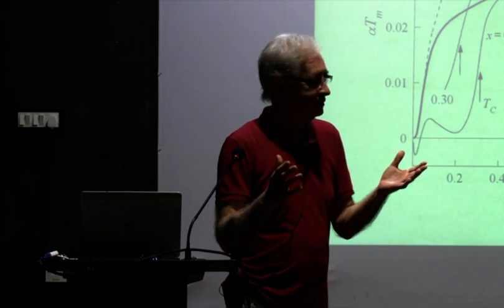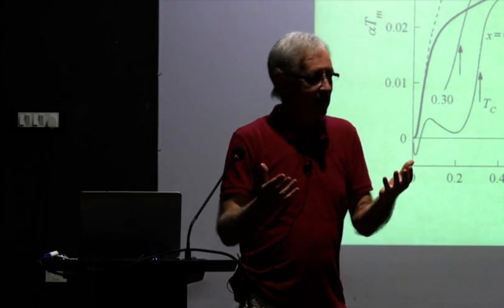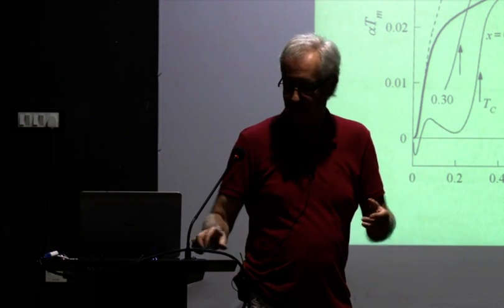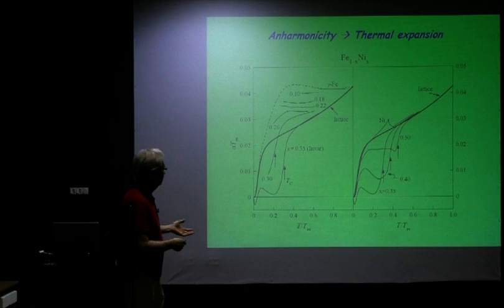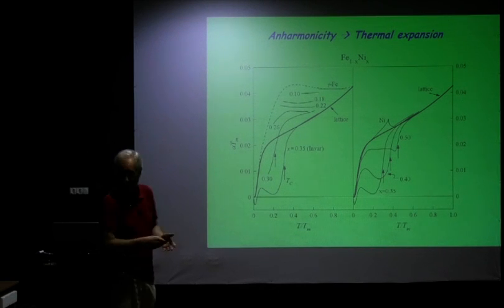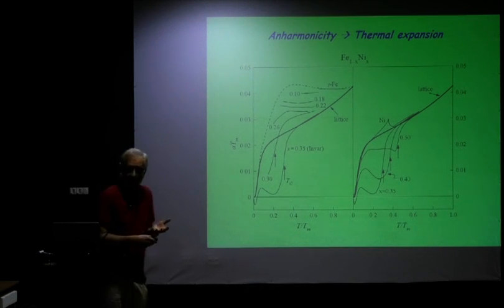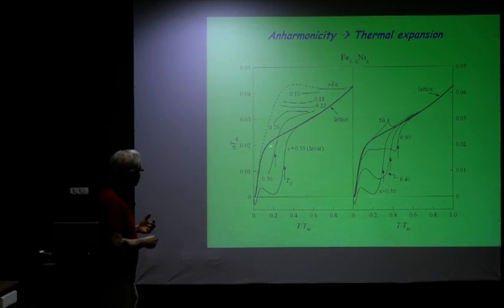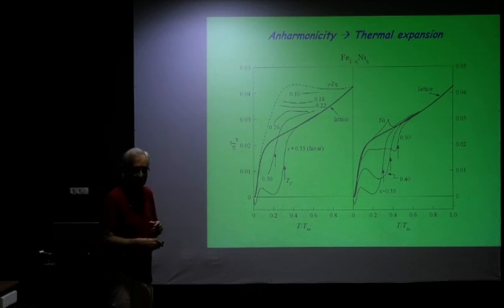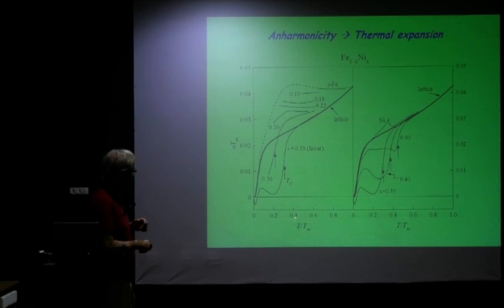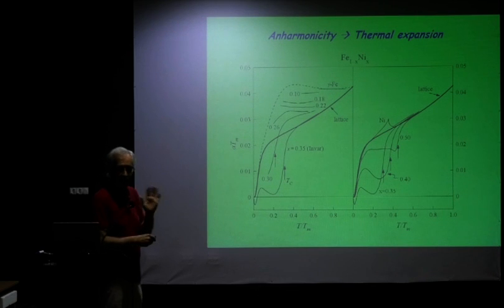He said, let's take these materials and measure their thermal expansions and see how they behave in the face-centered cubic state. This curve over here, this thick line, is our general lattice expansion. And we've plotted here again the reduced temperature dependence of alpha Tm. This is iron. That's gamma iron. Okay?